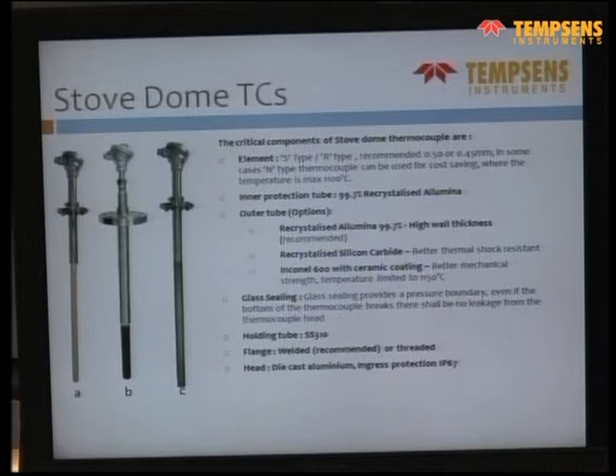As Mr. Clem was telling, silicon can have a lot of drift effect on the platinum thermocouples. So you need to have a protection of ceramic which will insulate it from the metallic part and reduce the possibility of silicon getting into the platinum and drifting the sensor. So in all three cases we are using S-type material. Also N-type is used in some cases, but inside would be ceramic and outside can be ceramic, silicon carbide, or inconel in the third case.